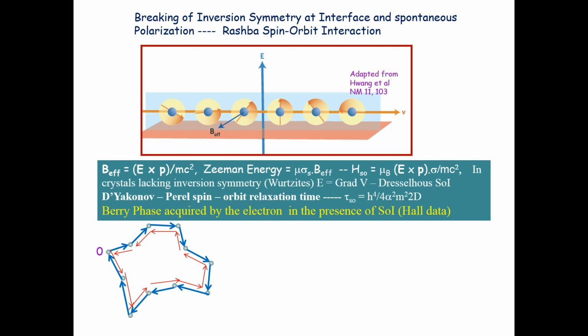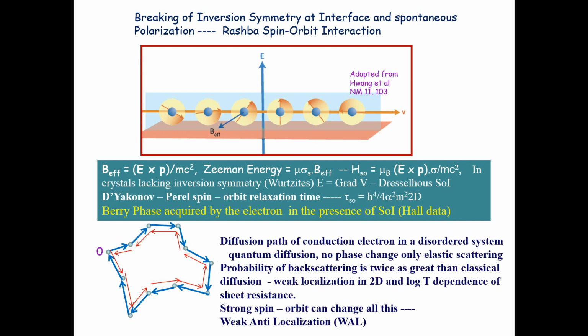Now as you increase temperature, instead of having only elastic scattering, you will also have inelastic scattering. And inelastic scattering is not a phase conserving process. So you kill weak localization just by raising the temperature. But if you also have spin-orbit interaction, and the spin-orbit interaction is strong, then these partial waves will acquire an additional phase and you will kill the constructive interference. So this phenomenon is called weak anti-localization. If you see signatures of weak anti-localization in your system, then you can say with confidence that there is Rashba spin-orbit interaction dominating the transport at very low temperatures.